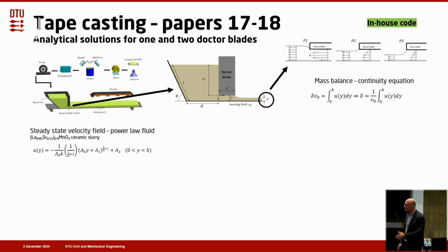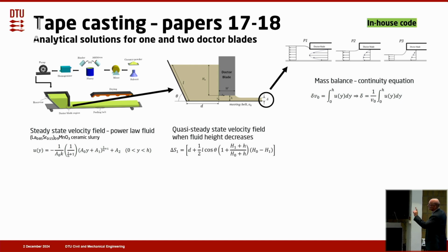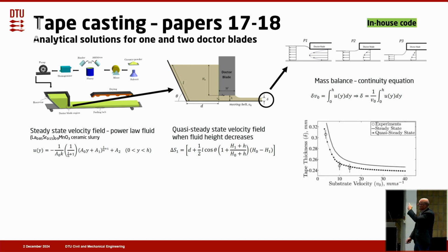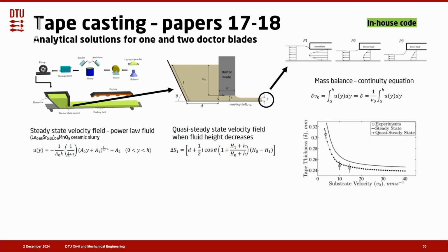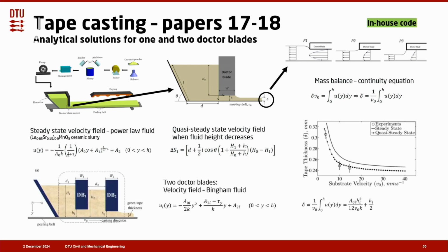So we looked at a power law fluid, suggested this. But what we also did was that we augmented this. So it became a quasi-steady-state velocity field when the fluid height decreases. Because when the pressure height decreases, it will change the velocity field. So this we suggested as well, and that was really the novelty of that paper. And we could actually get very nice results as compared to experimental findings. We also looked at two doctor blades, because with two doctor blades, this is actually where you can better control the height of the reservoir. And then we gave some contributions to the literature with the velocity field, also for a Bingham fluid.